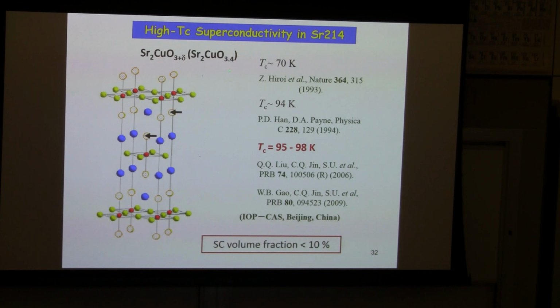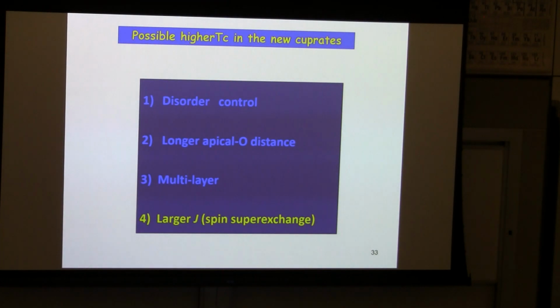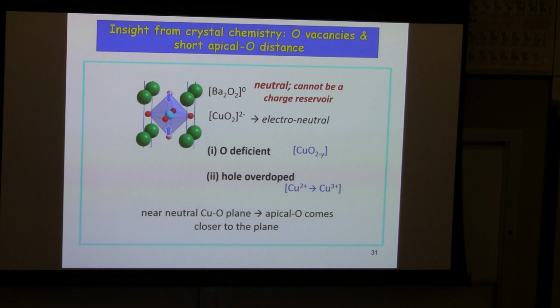But unfortunately, this material is not suitable for further studying because the superconducting volume fraction is always small, so that we cannot identify which phases, which structure is responsible for the superconductivity. On the other hand, barium-214 is a very good material, which shows bulk superconductivity. Superconducting volume fraction almost near 100%. And from the structure analysis, it's a single phase material. In the following, my talk is my own speculation based upon this oxygen deficient structure.